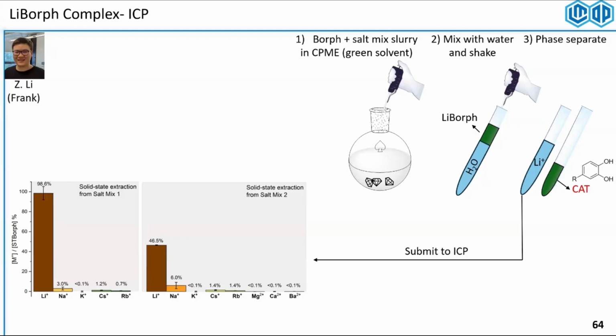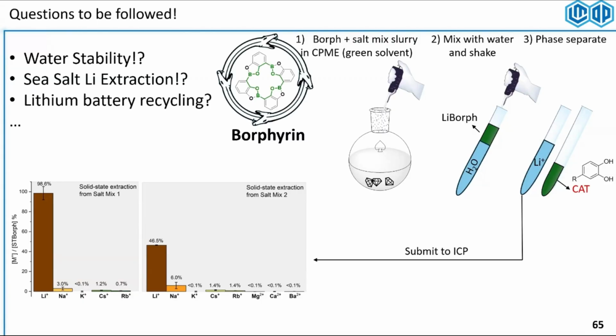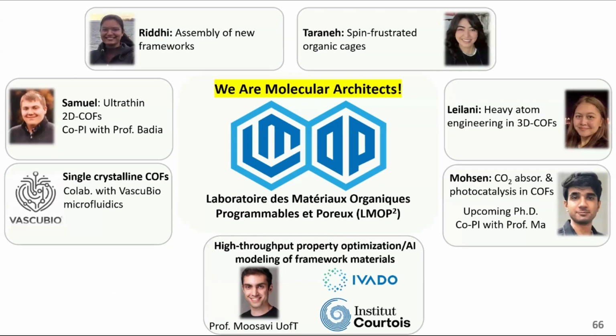What we noticed was when we had magnesium sulfate and other sort of desiccant salts inside the cocktail, the lithium absorption capacity in the time frame that we optimized comes down. So we had a hypothesis that maybe it's water assisted, like you need a little bit of water inside this etheric solution to be able to extract the lithium from the crystals. But there are still many open questions for this project that need to be answered. The water stability, can we fix the water stability of these? Can we do sea salt lithium extraction? Can we do lithium battery recycling with these macrocycles? This is an ongoing question that we're trying to fix.